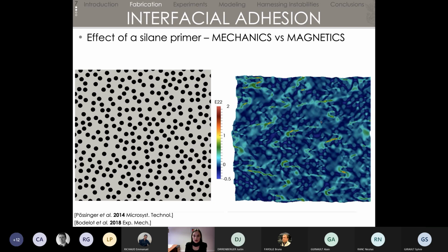In the mechanical tests, what happens is that those particles are entangled in the chains, and as you unfold the chains, they do not see locally large strains. So the conclusion for us was, in the end, we do not need to do a pre-treatment of the particles if we are doing just mechanical tests. But if we are planning on putting these samples under magnetic field, then we absolutely need to do a pre-treatment if we want to assume that our material is incompressible.